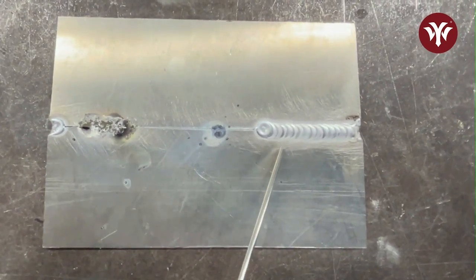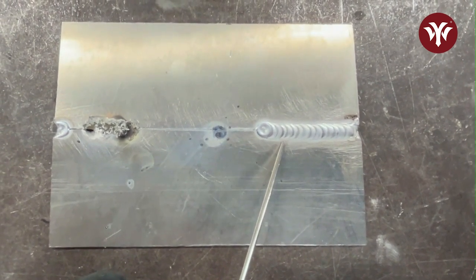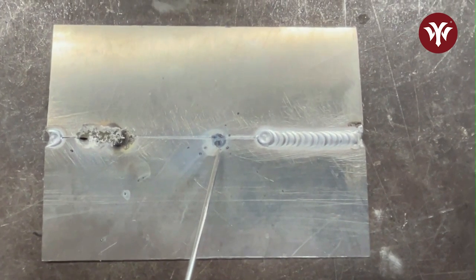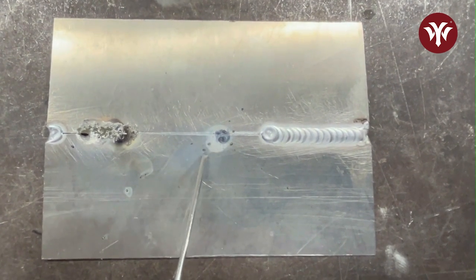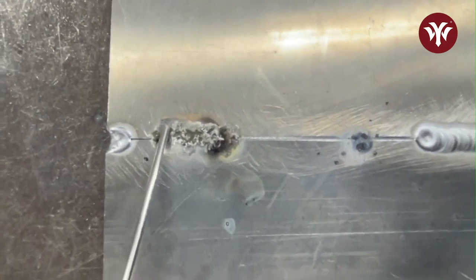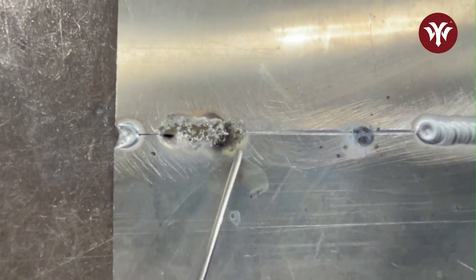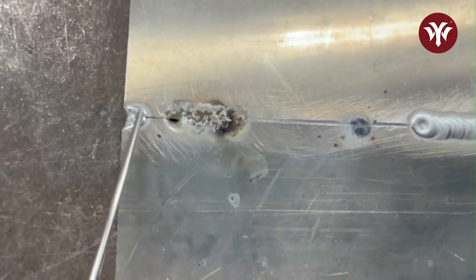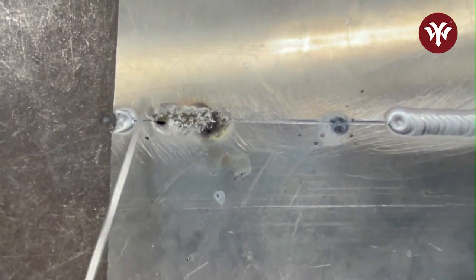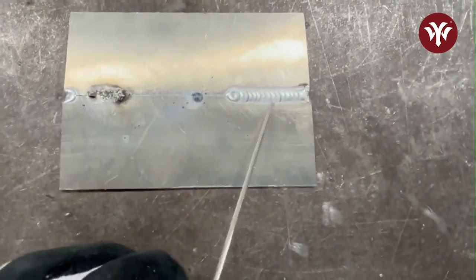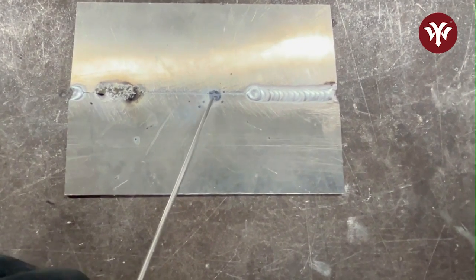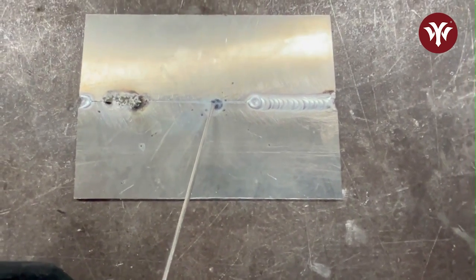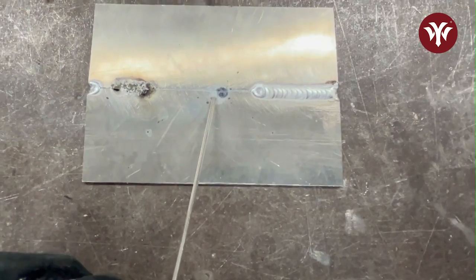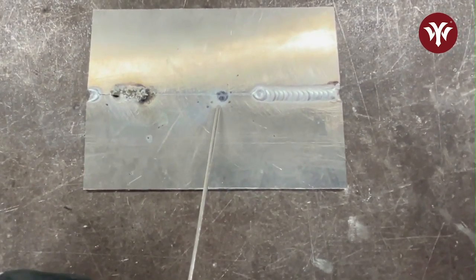Here I laid down a bead for comparison with approximately 12 to 15 CFH because I'm using a number 6 nozzle. In the center, I dialed that back, but it was next to nothing, and it burnt up the tungsten and spit it out and created a lot of black soot. So then I turned up the gas just a little bit more, and you can see what happens here. It melts the material, but it has no cleaning action really, because there's atmosphere pouring in, and it's just gonna create a completely sooty, it's just gross. So if you're getting welds that have a lot of soot in them, or just don't seem to have good arc control, or your tungsten is turning black and burning up, you probably have a gas issue and contaminants getting into your arc or weld zone.